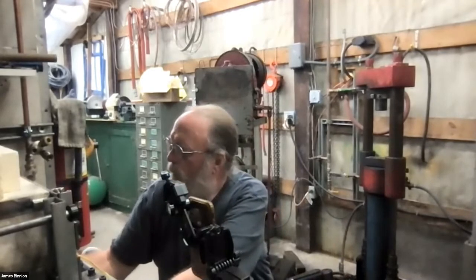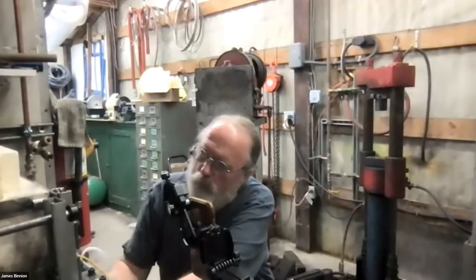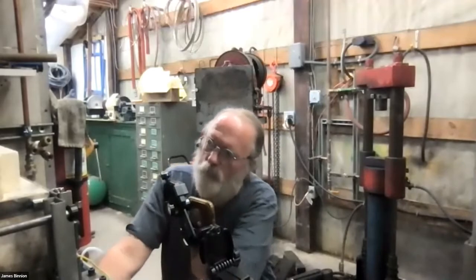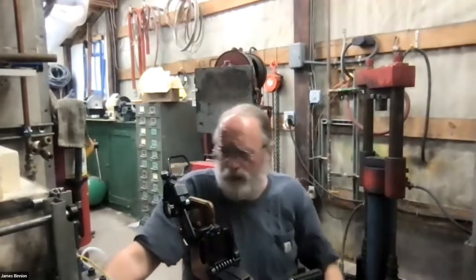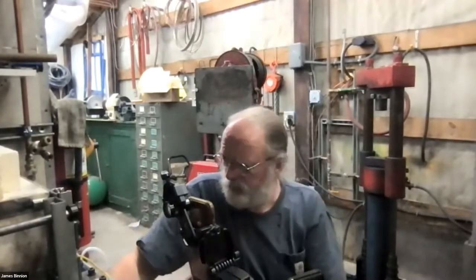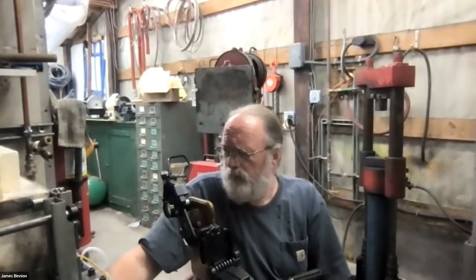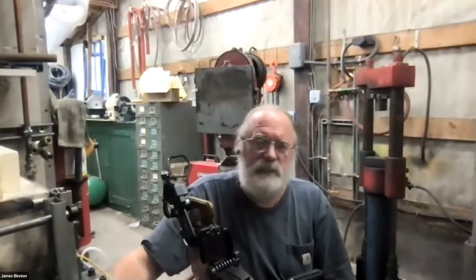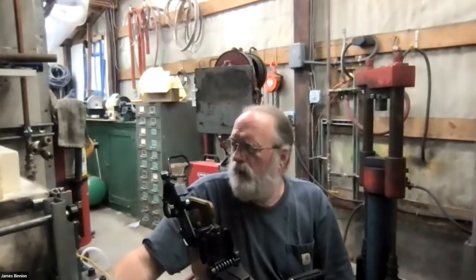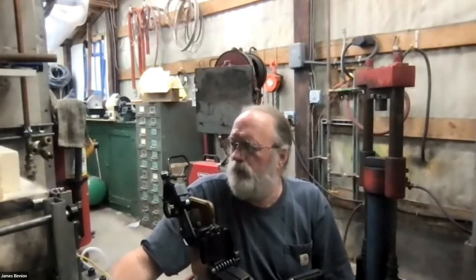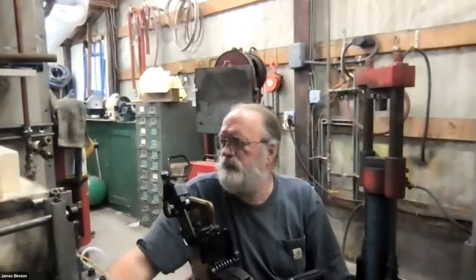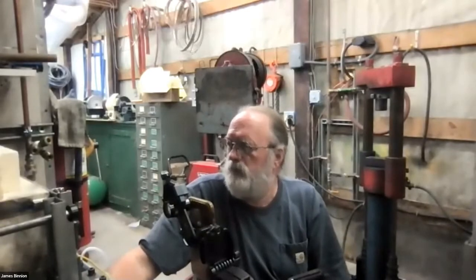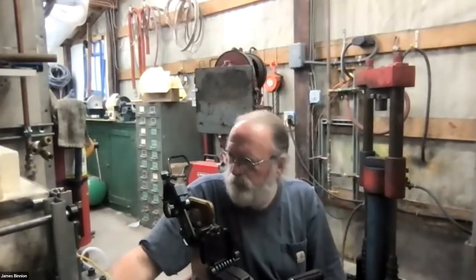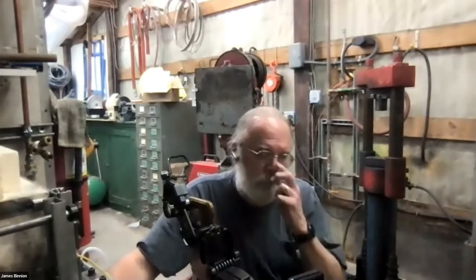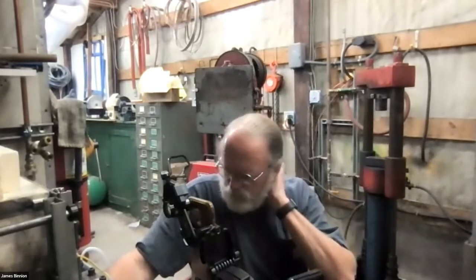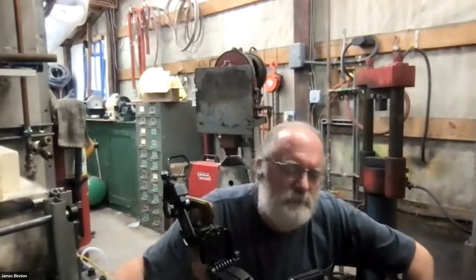Yeah. So this billet that you made, it looks like all the pieces were about 2 inches square, somewhere in that range to start with. 1.5 for the starting size. So mostly 18 gauge sheet. Well, it's 18 gauge for the copper and the bronze, and the brass is about half that thickness. So about 20 gauge. Okay. I'm sorry, 24 gauge. Yeah, go ahead.